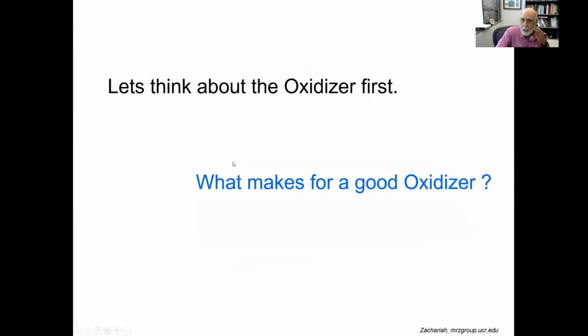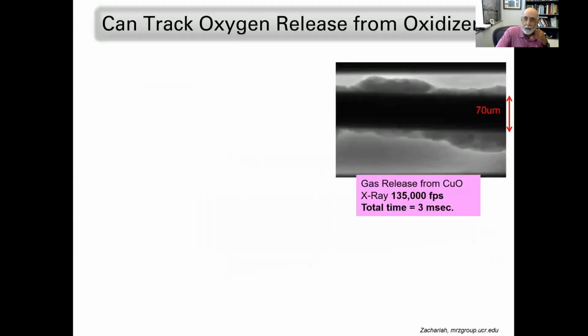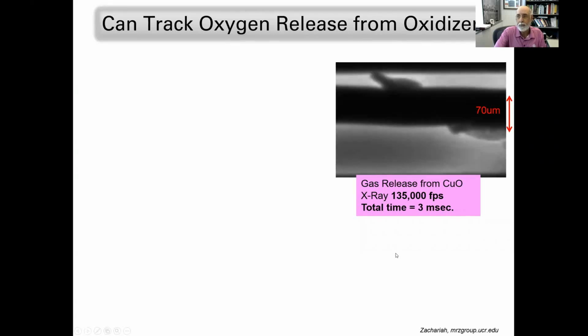So let's think about the oxidizer. So here is copper oxide. I've just taken copper oxide. There's no fuel here. And I'm going to heat that up on the wire. This is a 70 micron wire. And you can see these are nanoparticles. And you can see this bubbling going on. That bubbling is because oxygen is being released. It's an oxidizer for our purposes. So if you heat it up, you're going to get oxygen coming out.